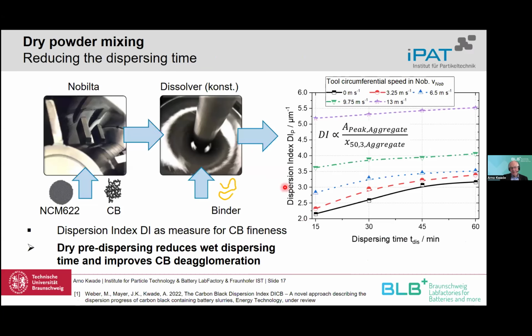And if we have this dry premixing compared to without premixing, what is shown here: the black curve means there's no premixing. Then we start at a certain dispersion index, and we can reach about 3 after 60 minutes. But if we have a certain premixing, you see that we start at a much higher dispersion index, or we have it already after 15 minutes, let's say. So it's much more effective than the wet process, and we can also reach much higher values.